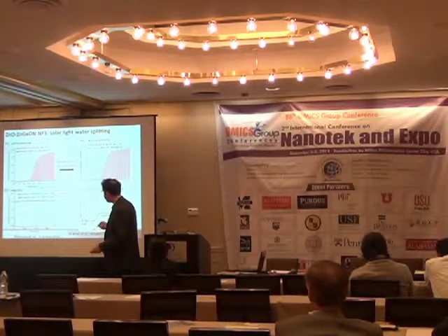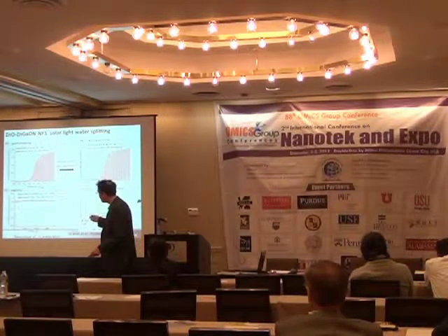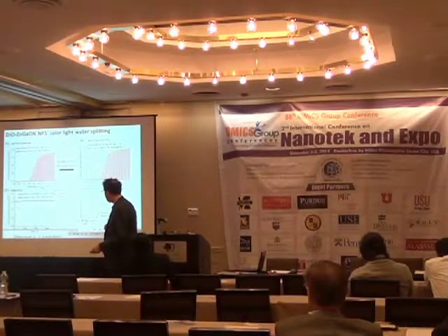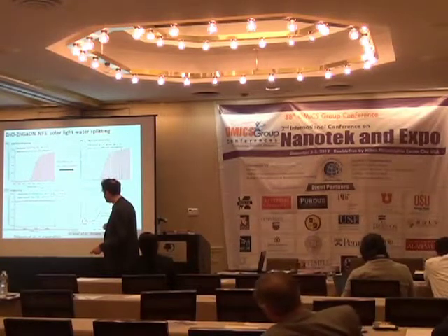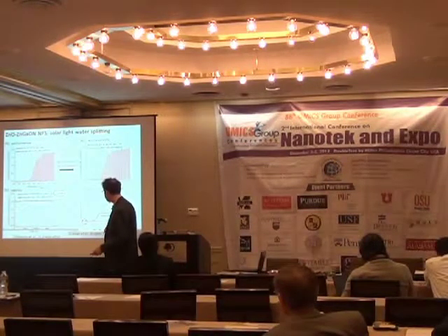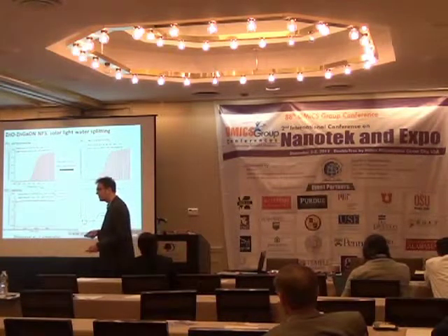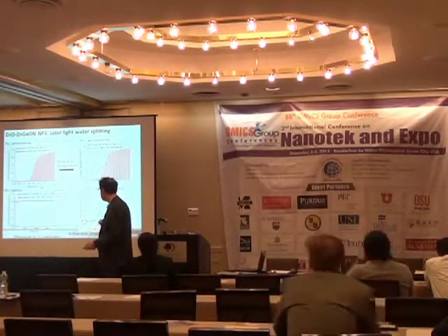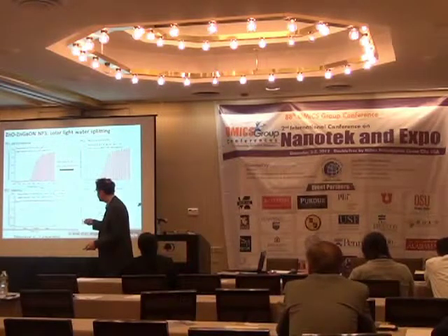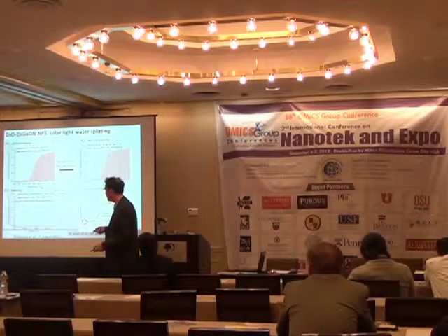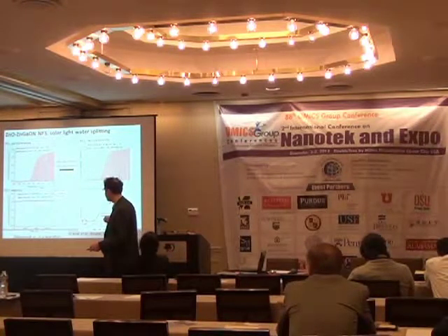And what is nice in our case is that the onset of the voltage for water splitting is quite low compared to other materials, for example hematite, which has quite a large value for the onset of the water splitting. So the problem is still the efficiency. The current is a bit too low compared to other materials, so we still have to work to increase the efficiency of that material. 1.5 milliampere per centimeter square is not such a high current. We should get something like 3 or 5 to get a quite efficient material.